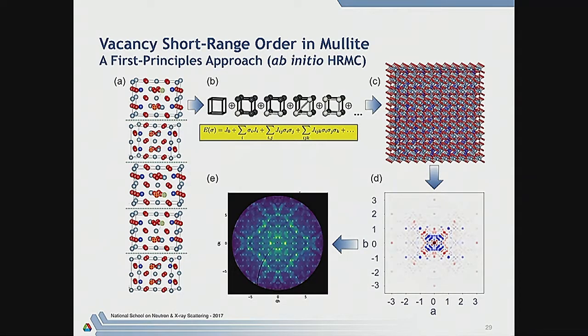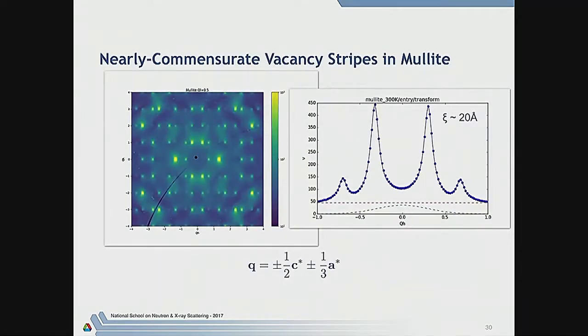And in principle, if you have to optimize these Jij, you can close the loop. Okay. So as I say, because of computational power, this actually might be a quicker way of doing it now than having to think about a problem for many months and optimize a whole set of energy parameters manually. But it turns out that we think that it nevertheless missed some of the longer range correlations that, for instance, are represented by these incommensurate wave vectors.